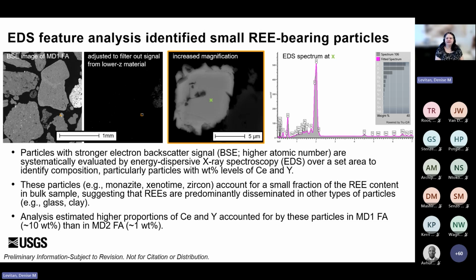So to look at this a little bit more specifically, we looked at these samples again on the scanning electron microscope with the energy dispersive X-ray spectroscopy, which is a lot easier to say when it's just EDS. But the way that electron backscatter signal works on an SEM is that elements with higher atomic numbers, or like further along the periodic table, are brighter in backscatter. So because the rare earth elements generally have higher atomic numbers, like 50s and 60s for the lanthanides at least, those atomic numbers are a lot higher than like 13 and 14 for aluminum and silicon.